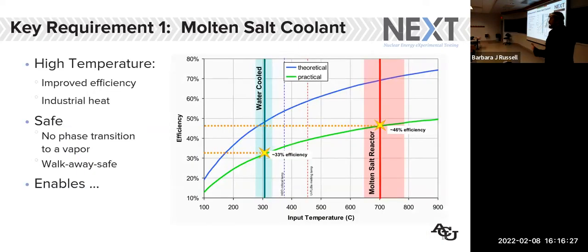The other advantage of having molten salt as our coolant is we're not limited to a few hundred degrees like pressurized water reactors using water as our coolant. As soon as water wants to get above 100 degrees centigrade, it wants to do a phase transition, so we have to have high pressure. And that brings in all sorts of dangers and hazards in itself and expenses to mitigate against it. But if we use the molten salt as our coolant, then we can operate at much higher temperatures.